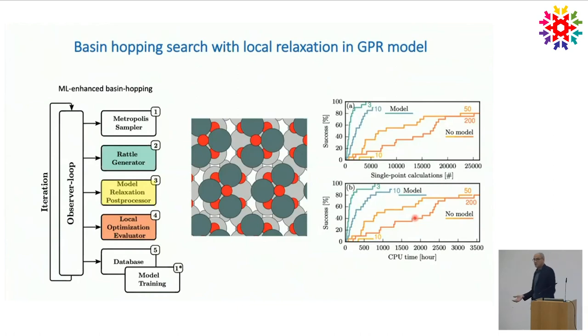I mean, if you start a simulation and you sit down and wait for it to find the solution, then you need to wait about 2000 hours with this type of search before you have 50% likelihood of having found the global minimum, which is the one depicted. So I mean, it's stochastic. You can be lucky and find it right away. If, after 500 hours, you might have found it in every 10th of your independent searches you have started.